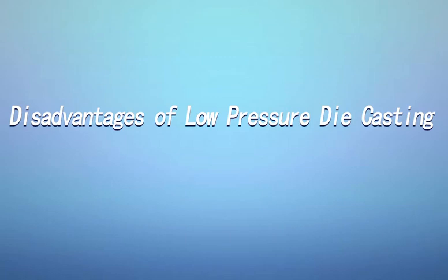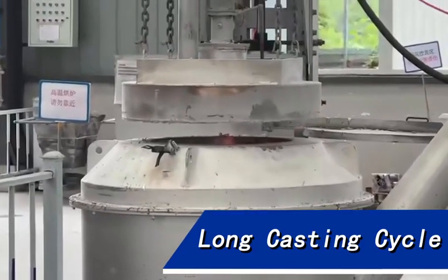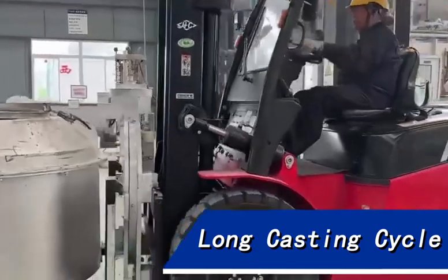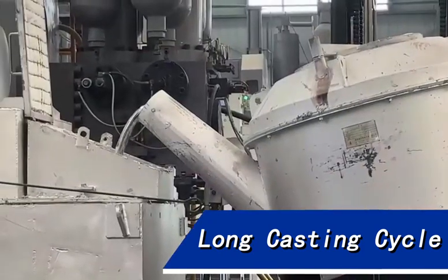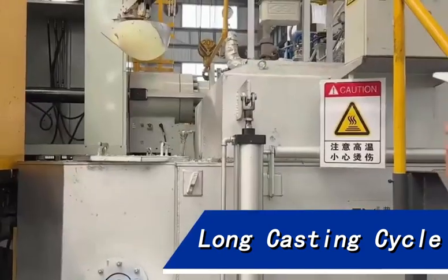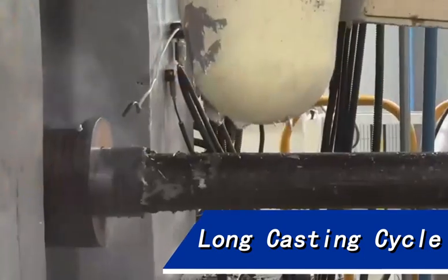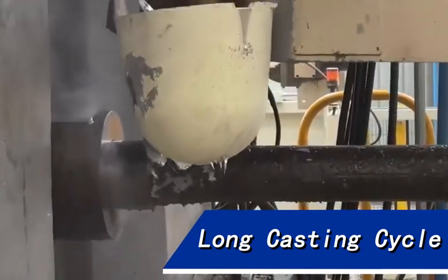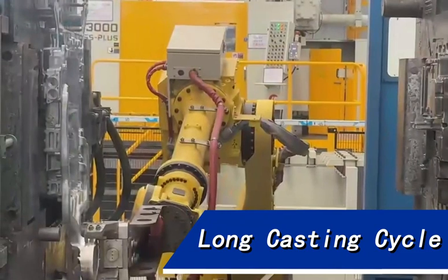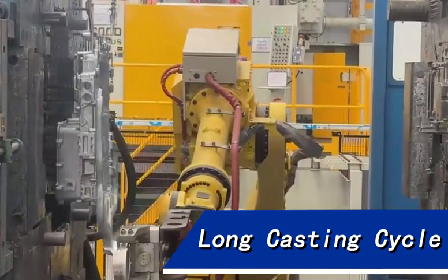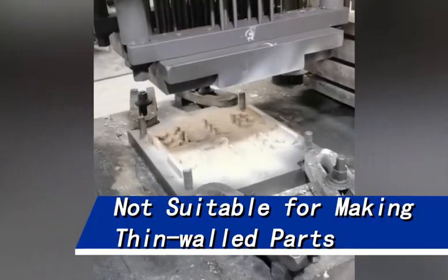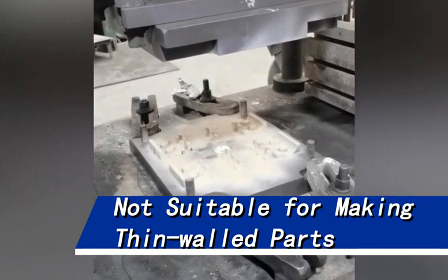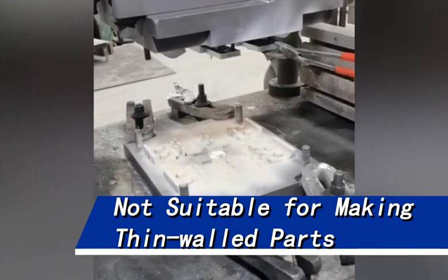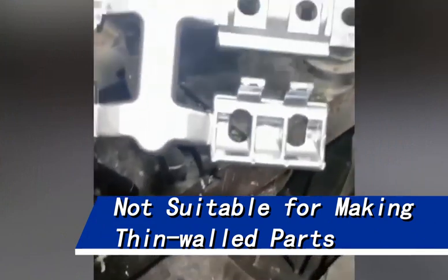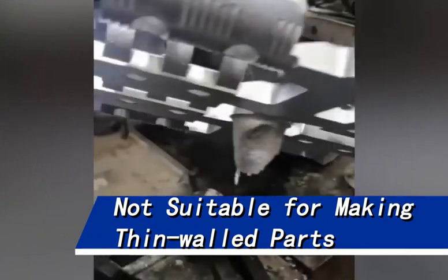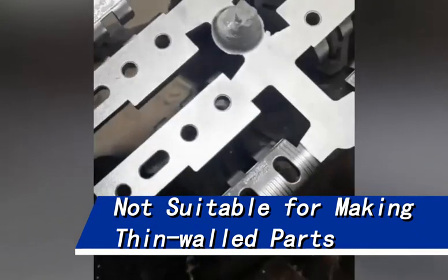Disadvantages of low-pressure die casting. Long casting cycle. A drawback of the low-pressure die casting process is its slower cycle, primarily due to the low pressure involved. As a result, the process has a low production rate, making the manufactured parts relatively expensive for large batch productions. Not suitable for making thin-walled parts. Low pressure means it is hard to push metal flow into narrow areas like thin walls. The minimum wall thickness of low-pressure casting parts is 3 millimeters.